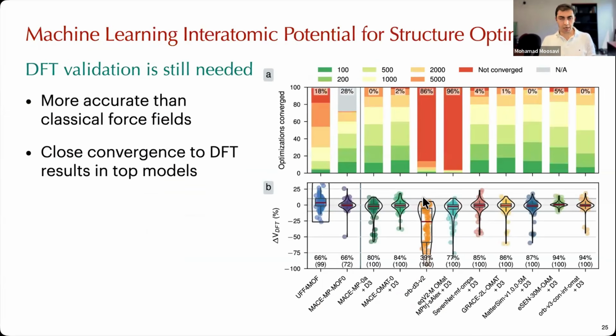And in particular, if you are evaluating them for crystal structure optimization, this is the performance of all sorts of models compared to DFT. So we take a crystal structure, we do DFT optimization, and we take it as a reference, but then we take all sorts of machine learning potentials and do optimization, and we compare the delta volume in the final crystal.